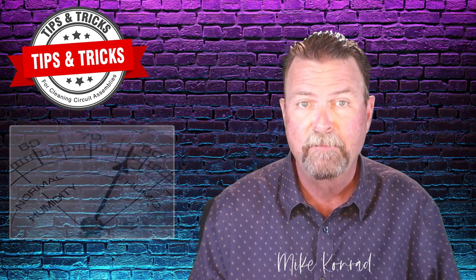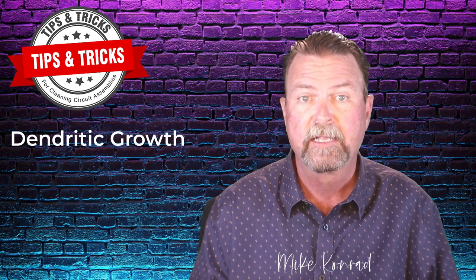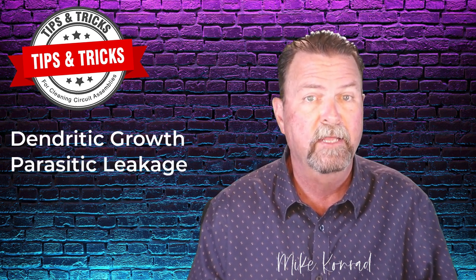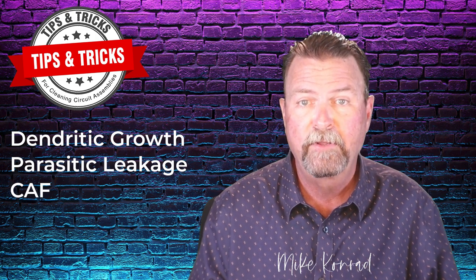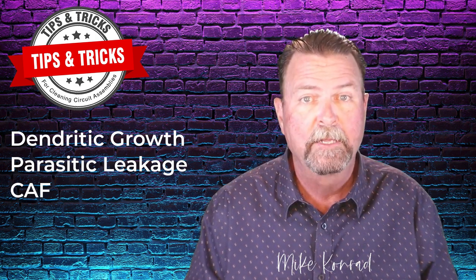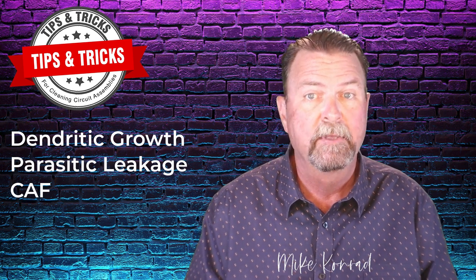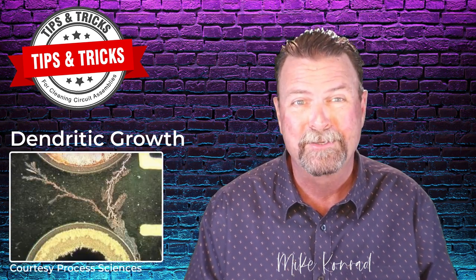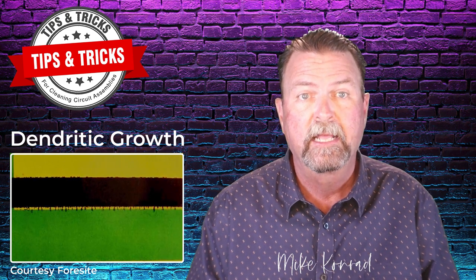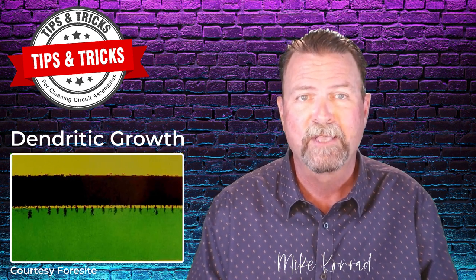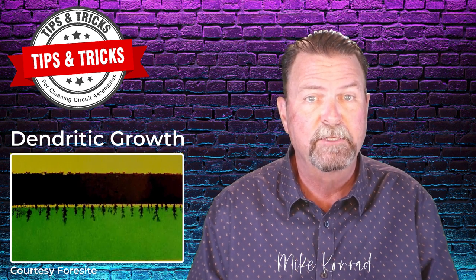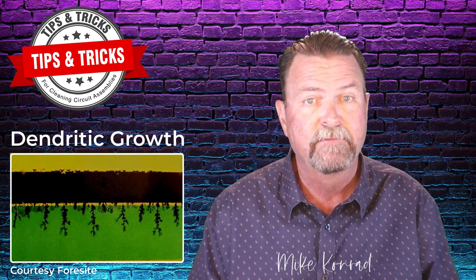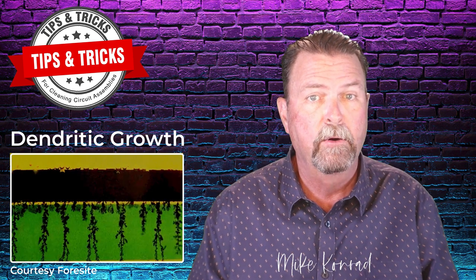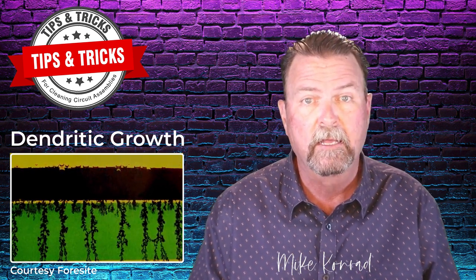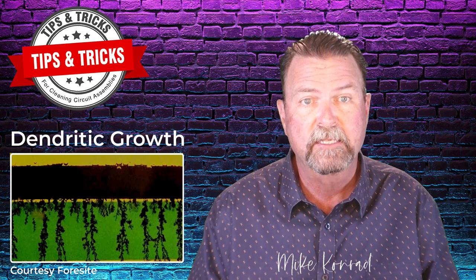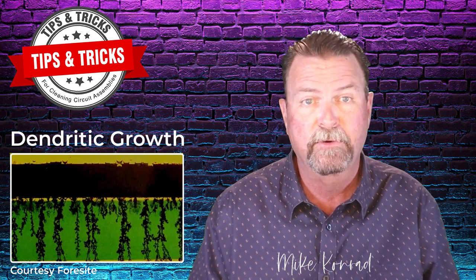Electrochemical migration failure mechanisms fall into three categories: dendritic growth, parasitic electrical leakage, and conductive anodic filament, or CAF. The most common and most severe manifestation of ECM is dendritic growth. That's where all the drama occurs. Here you can see dendrites growing in real time, thanks to our friends and colleagues at Foresite. The metal structure growing between the anode and the cathode is conductive. While the conditions to make this video were ideal, allowing the dendrites to grow rapidly, normally, in the field, dendrites take between weeks and even months to grow.